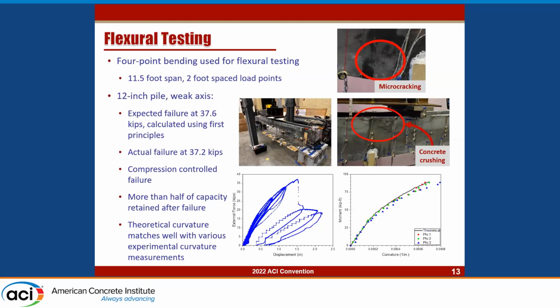But along this force displacement curve, we start to see that we're deviating from our typical path around 30 kips. That's when we started hearing cracking noises. So that's when we started getting more damage occurring. We continued to load until failure, which occurred at 37.2 kips. It was a compression controlled failure. And then once we unloaded and reloaded, we still retained about half of that capacity. So we had some good residual strength in there.